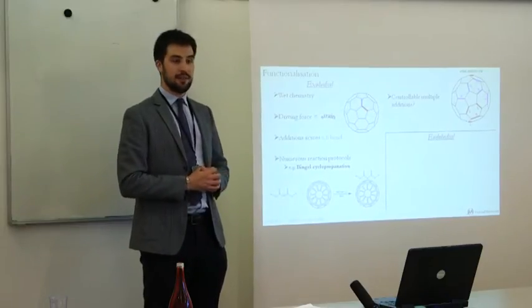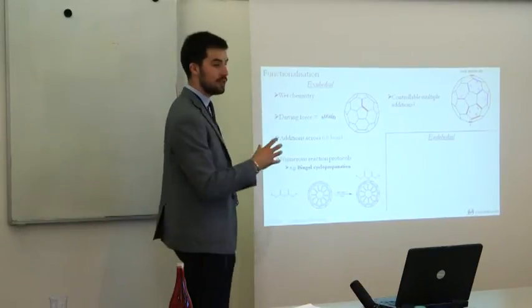We can actually functionalize these things. We've got these cages. It's very nice to look at. It's some cool science. But we want to do something useful with them. The beauty about fullerenes is that, given their electronic structure, you can actually change them on the outside and the inside. On the inside, they're very inert, which means that we can capture species in there. Atomic, ionic, and molecular. That is endohedral functionalization. And exohedral functionalization is attaching things onto the outside. They actually behave like any sort of normal alkene you've learned in GCSE. There's a nice carbon-carbon double bond. You can do standard alkene chemistry on them. It involves a lot of solution-based wet chemistry.